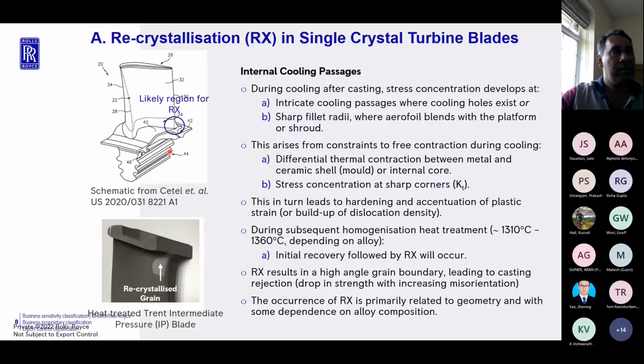inserted into the disc. But as you would immediately see, the internals of this blade have got cooling passages like you saw in the previous slide, but also you get these sharp radii of curvature, where the aerofoil blends onto the platform. Now, these internal cooling passages, as well as these very sharp radii of curvature, are regions where potentially you can have stress concentrations or plastic strain that develops. So remember, when you cast, you're casting metal around a ceramic, and both the metal and the ceramic do not have the same coefficient of thermal expansion.